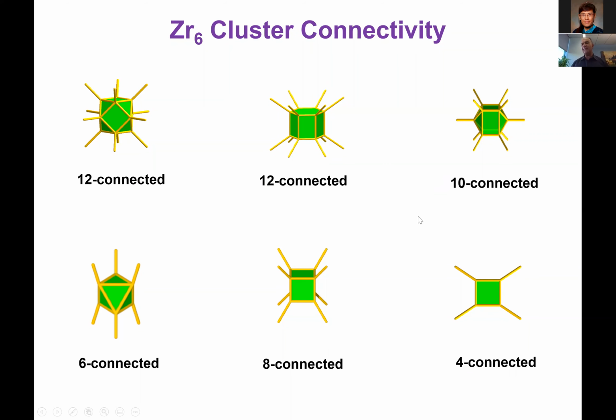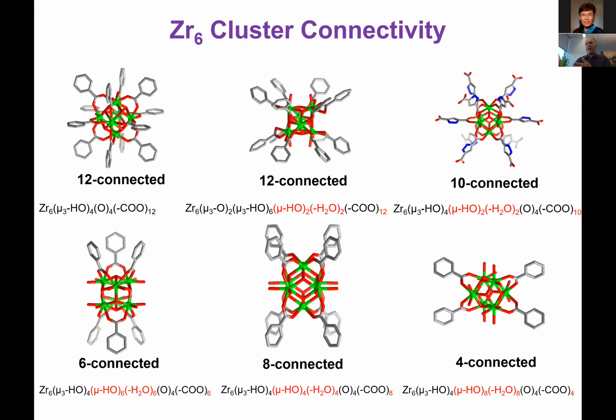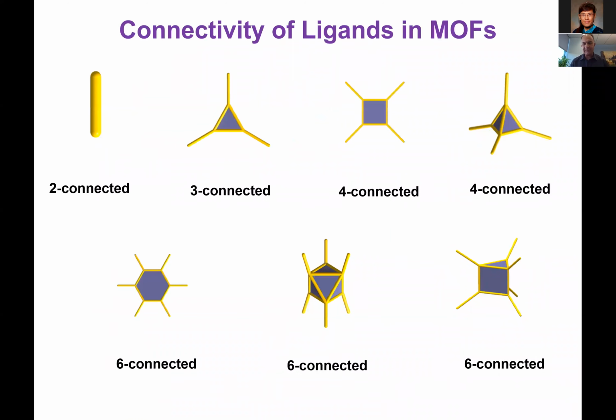10 connected means you have only 10 carboxylic acids and still zirconium-6. In order to balance the charge, for every missing carboxylic acid you will have a water and a hydroxyl balancing the charge all the way to 4 connected. You could even make a square in directionality point of view with 6 zirconiums. If you go from geometric entities to chemical entities, that's how they would look like, and these are the formulas.